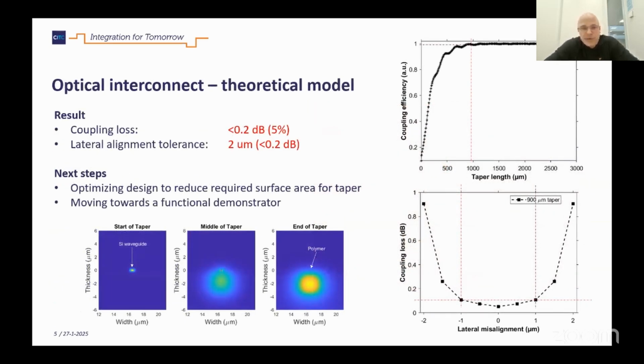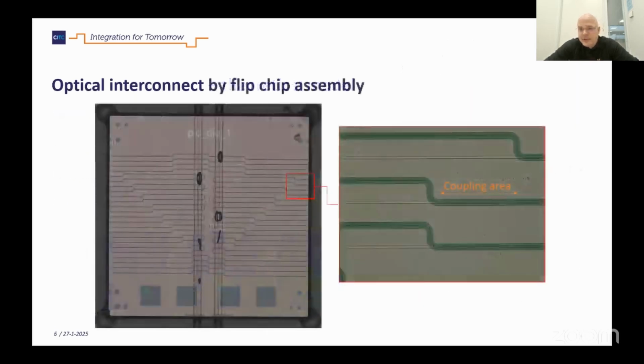But we are also working towards the optical interconnect. Here we rely on evanescent field coupling, and we have optimized the design from PIC to the polymer waveguide structure, where we have significantly less than 0.2 dB loss at the interface, still with a relaxed alignment tolerance of 2 microns. This is where we partner with Vario Optics. They provide us with the technology, and we make our own photonic test die to demonstrate this technology building block. This is one of our first assemblies, where you see the polymer waveguides merged together with the photonic circuit. We are currently evaluating the performance of this assembly.